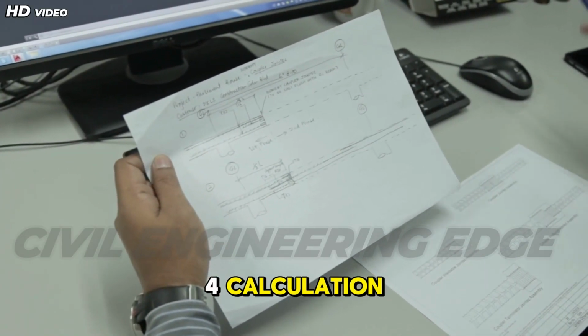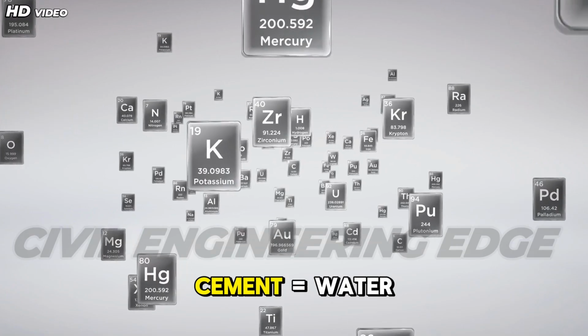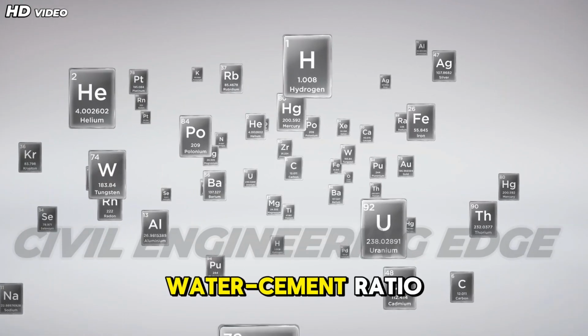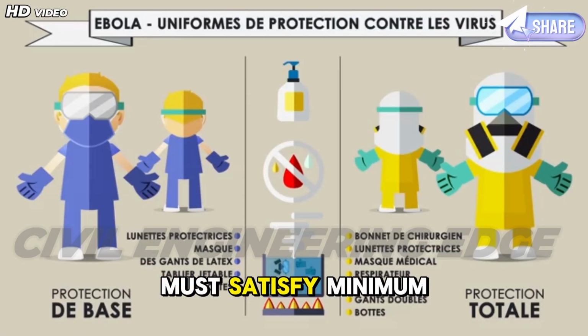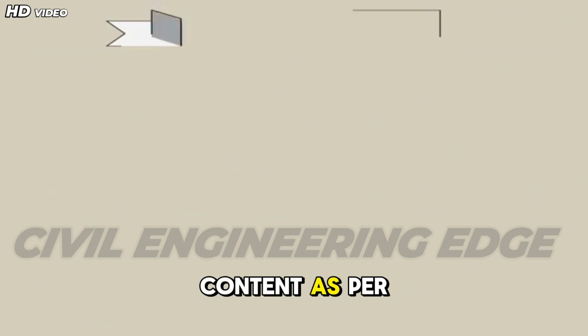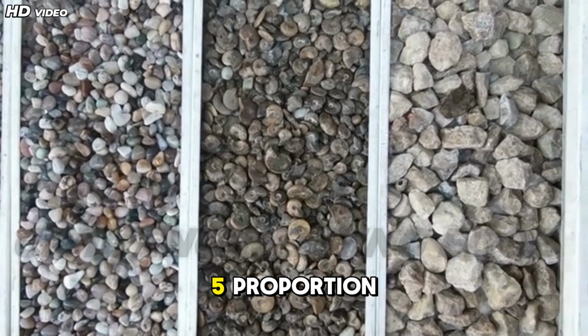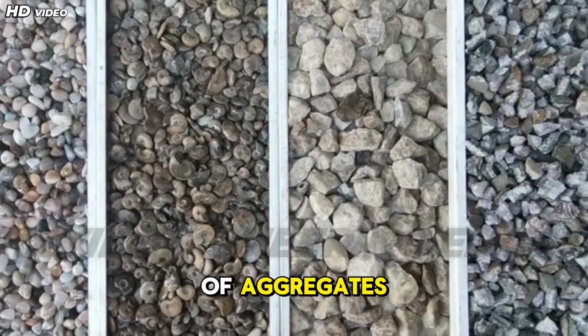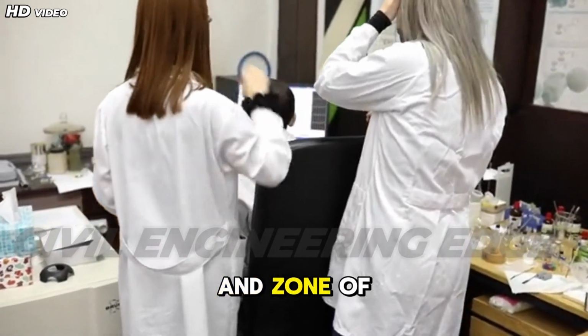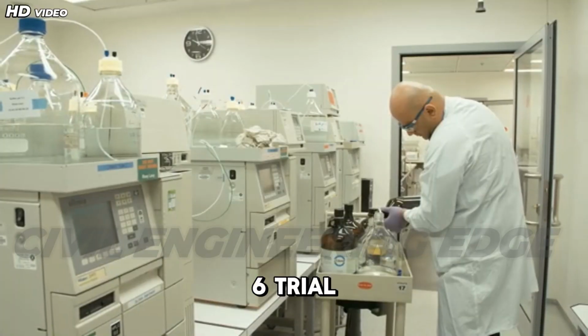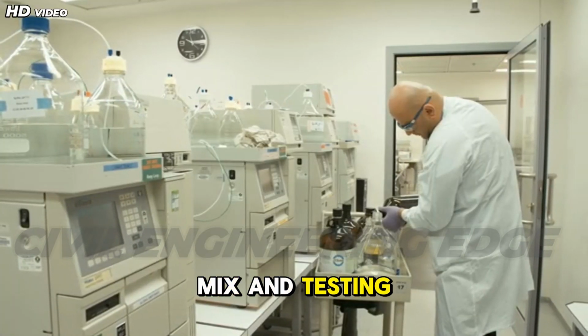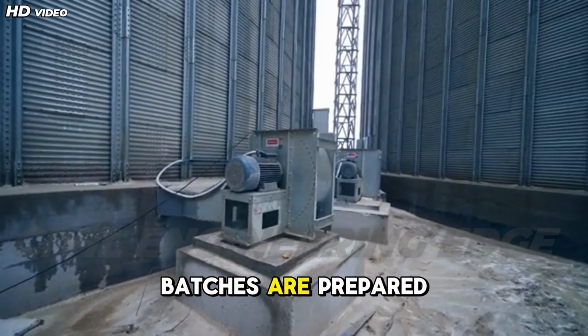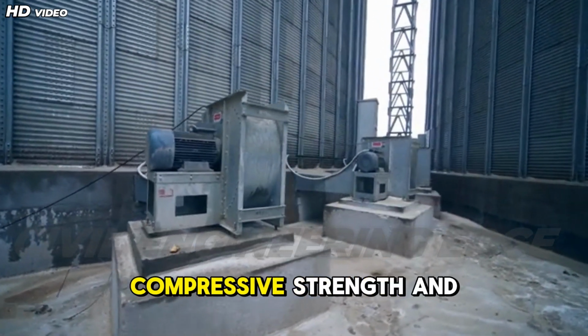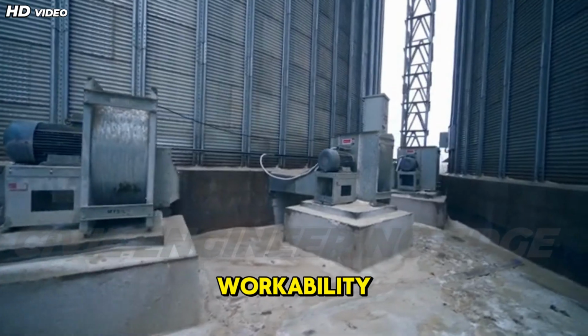4. Calculation of cement content. Cement equals water content divided by water-cement ratio. It must satisfy the minimum cement content as per exposure condition. 5. Proportion of aggregates, based on aggregate grading and zone of fine aggregate. 6. Trial mix and testing. Laboratory trial batches are prepared and tested for compressive strength and workability.